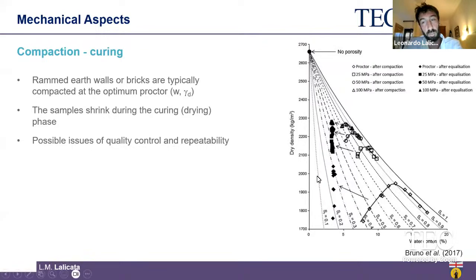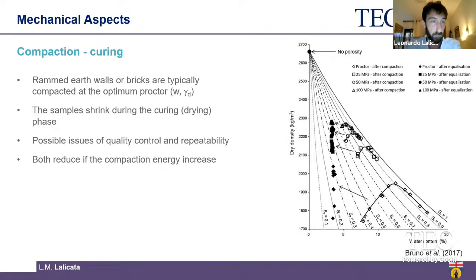One option to reduce that: you see your points will move from this curve in here, and they will go to the left, because the sample will lose weight and lose water content, approximately 3–4%. And you see there is a lot of variation in this data. One option is to increase the compaction energy. For instance, for these points here, we are increasing the compaction energy, and then the drying, the curing process, induces a much lower change in density and also in shrinking, obviously.